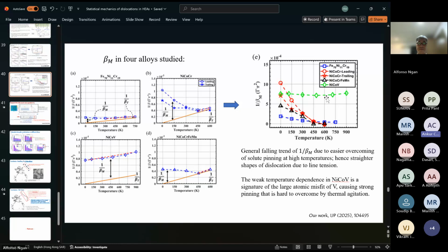One more query with respect to high temperature I have is that, of course, you have not addressed this in this talk, but maybe I would like to have your view. When you have simultaneous dynamic solute segregation at the faults and also at the Cottrell atmosphere, you mentioned that the Suzuki segregation plays the bigger role compared to the Cottrell atmosphere. But can you comment also on the dynamic environment just ahead of the leading dislocations, which is evolving because of this segregation environment while we are testing at higher temperature? How do you visualize this interaction in that sense?